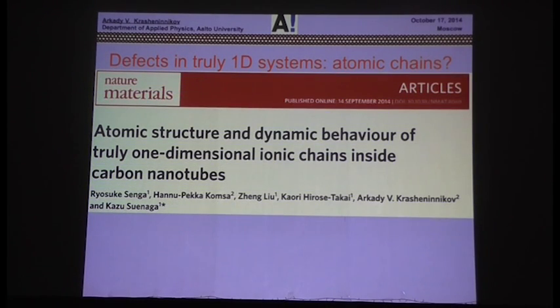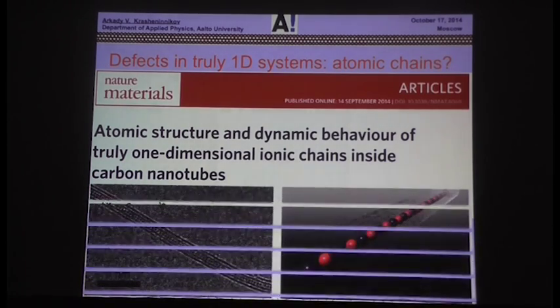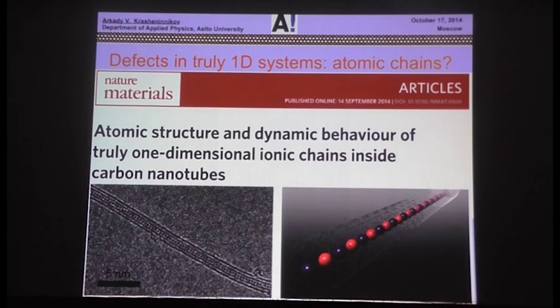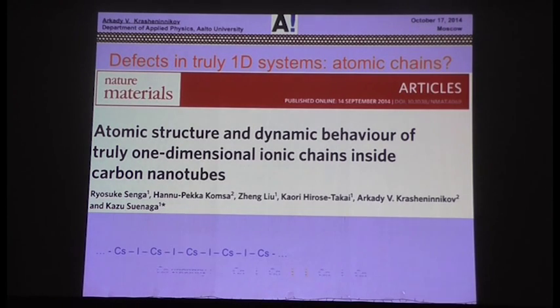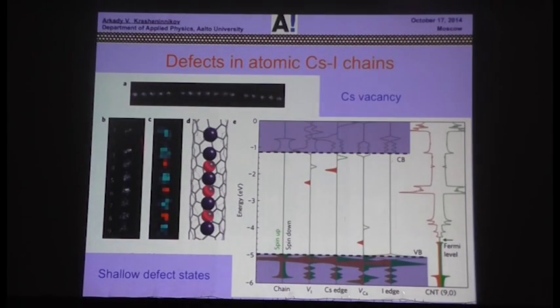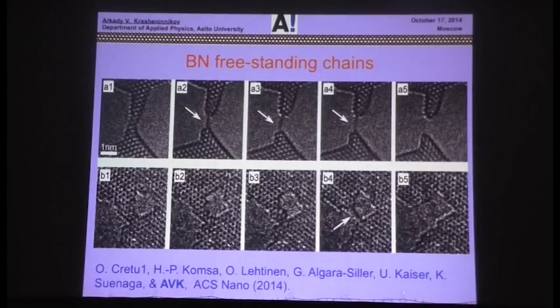And as I promised already, just 1 minute. Recently, we published quite, in my opinion, interesting papers about defects in a one-dimensional system, truly one-dimensional. It's a one-dimensional salt inside a nanotube which served as a container, and there some defects are possible. For example, cesium atoms can be missing or the other way around, and again, microscopists, our coworkers, saw these defects, and we try to explain the experiments and also explain the electronic properties which the material may have. And another example of a one-dimensional ionic system is a boron nitride chain made using a top-down approach, using an electron beam. We just cut extra material.